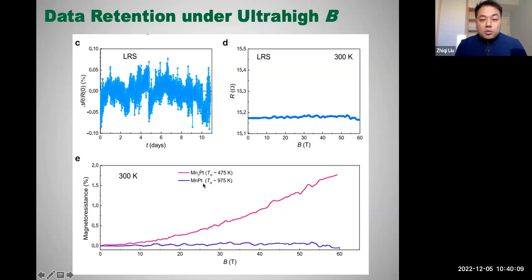If we think about why this is so robust, we can look at the Néel temperature, which is a characteristic of how strong your antiferromagnetic coupling is. For manganese-3 platinum, if you apply a 60 Tesla magnetic field, the room temperature magnetoresistance could reach around 2%. But for manganese platinum, the Néel temperature is much higher, around 500 K higher than that of manganese-3 platinum. We have a very flat magnetoresistance curve. That means the antiferromagnetic coupling is very important for the stability over strong magnetic fields.